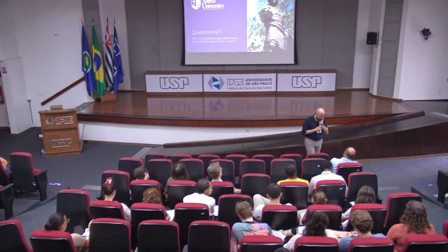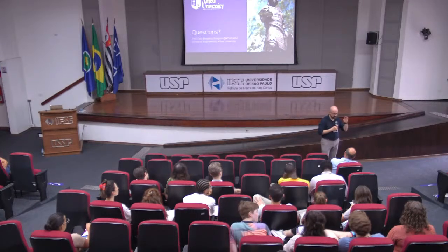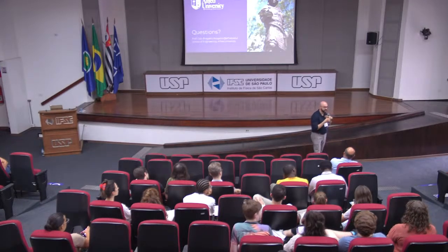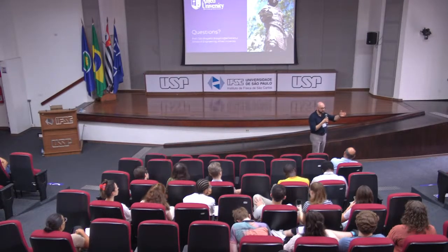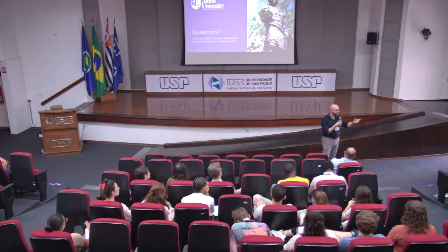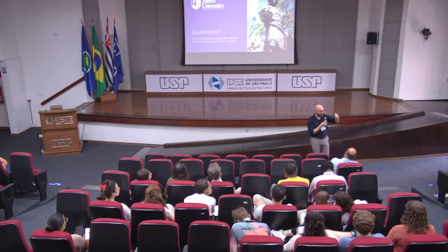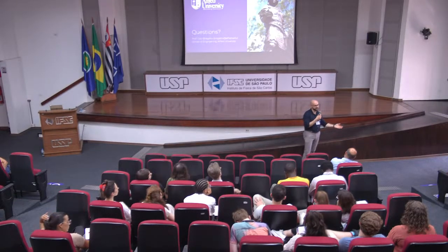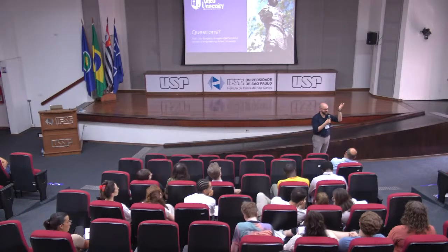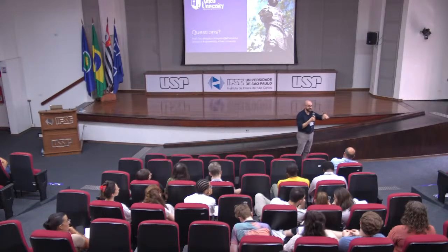That's a good question. I would say that there are some things that are going to be eliminated. I found a very small change in the ionic conductivity with the thermal history. Ricardo found a little bit bigger. But still, we're talking about one order of magnitude, right? And if you think about compositional dependency, we can vary by 6 to 7. I do not believe that either the mobility or the number of charge carriers is changing by 7 orders of magnitude, right? Putting all of that proportionality on just one of them seems a little dramatic.